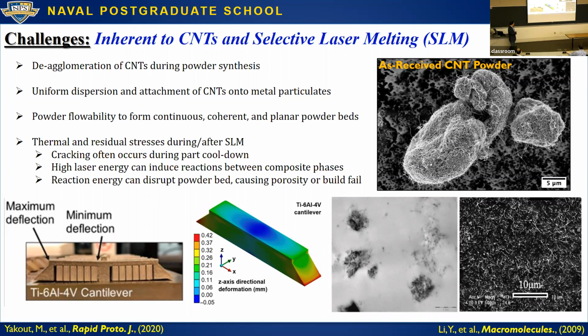You can actually do interesting studies where you 3D print material that, if it's under residual stresses, is going to deform by itself. It's going to deform, and you can quantify the residual stress state right as soon as it's printed. And you can do some modeling, etc.